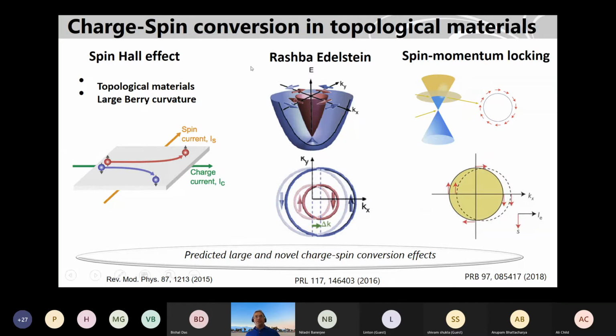Also, from the band structure point of view, there is a Rashba-Edelstein effect here. If you have this huge spin orbit coupling in a semiconductor, this band can split due to spin orbit coupling. And if you take a cut at any Fermi level here, you get two bands. So this is the inner band, this is the outer band, and you apply an electric field, you shift the Fermi sphere, so you actually accumulate these blue spins more than the red spins. And this spin polarization can be utilized for spintronic devices.